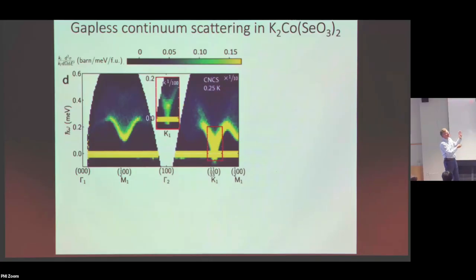So it makes sense that I have a fully soft mode at that point. Actually, if you look in greater detail, you see that there's also a finite energy component. So there's both a gapless mode that comes all the way down, and then also a mode at finite energy. And we actually know where that one comes from. That has to be there also when there is a density modulation.